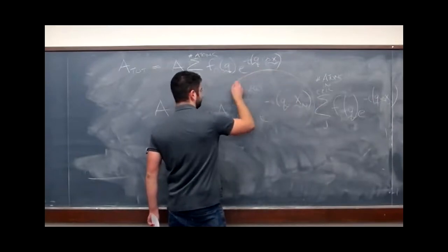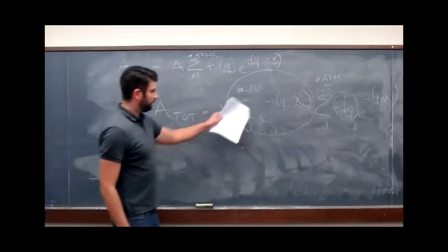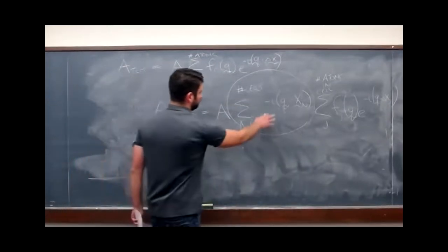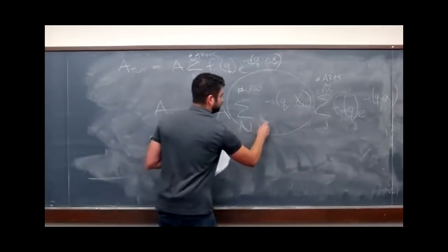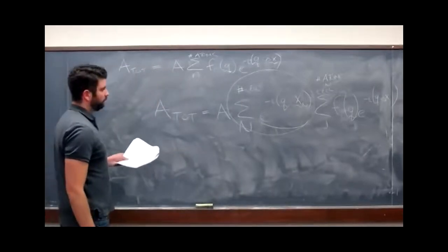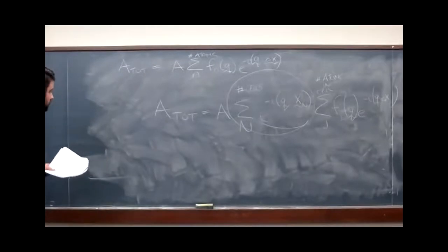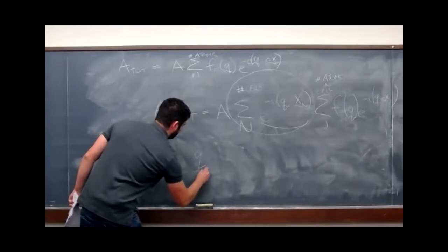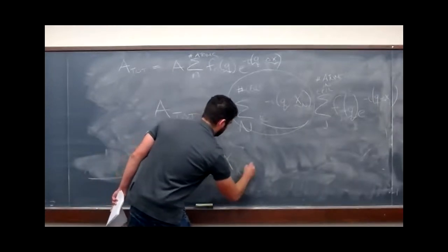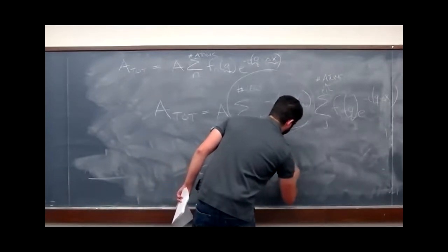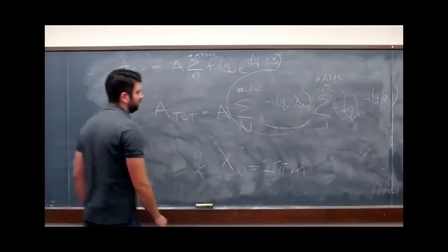And I want to look at this term here. We can see that this value can range from -1 to 1. But if we want this to constructively interfere, we want this value to always be equal to 1. And for that to occur, the scattering vector dotted with the unit cell position must be equal to an integer multiple of 2 pi. So this must occur for fully constructive interference of all the unit cells.